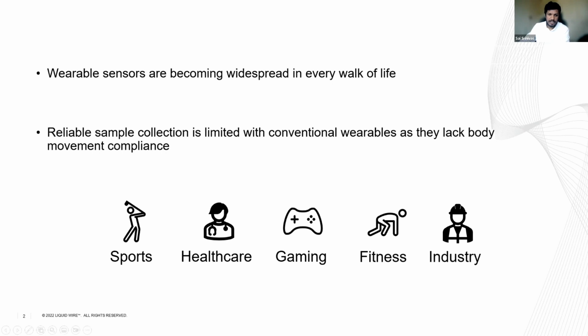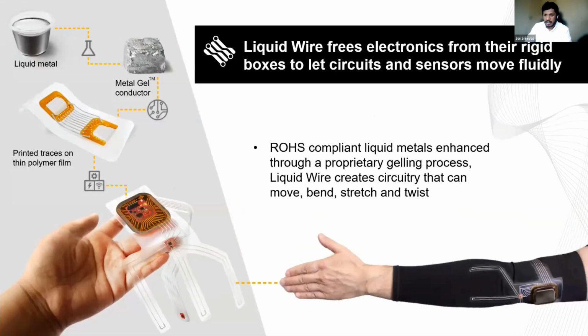To address that challenge, Liquid Wire comes in. The backbone of Liquid Wire is metal gel. Metal gel is an alloy of liquid gallium indium tin. We modify that alloy with some oxide microstructure and a few proprietary additives. When we make that mixture, it's in the consistency of peanut butter at room temperature or a much wider temperature range. So you can spread that peanut butter like a conductor on a thin piece of plastic film, and then you can laminate it with another piece of plastic film. Then you have a current carrying conductor or a strain gauge, which can be stretched, which can be flexed, and which can be washed. So this enables us to bring wearables much closer to the body and enable real-time monitoring of the human body without obstructing your day-to-day activities.